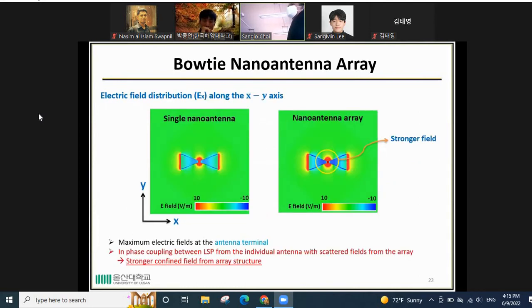Also, we analyze the electric field distribution along Ex. We can see from this field distribution that the electric field is maximum at the antenna terminal, and from this nano antenna array, you can see that a stronger electric field is provided at the antenna center because of the in-phase coupling between localized surface plasmon from the individual antenna and also scattered field from the array.